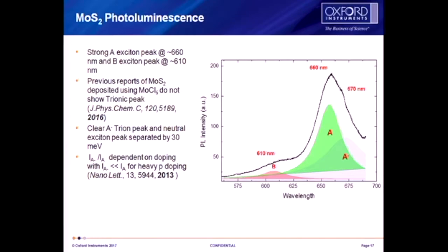And you can do this by the fact that molybdenum disulfide as a single layer has a very strong photoluminescence capability, which you don't see with a dual layer. And if you see here, this is very indicative of a single layer of molybdenum disulfide. There's a 30 meV gap between here, and also there's a peak around here, which we believe is induced by this trion peak and a neutral excitation separated by 30 meV.